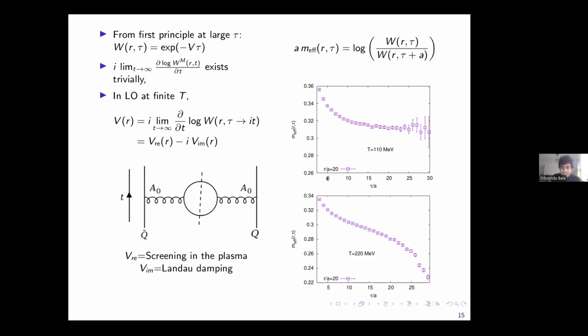But at finite temperature, as we just discussed, we do not see this plateau at all. What we have is a function that decreases gradually all the time, and we have to extract the potential from it. This tells us there is no pure exponential decay. How do I understand that? If we look into the leading order perturbative calculation of this potential, it turns out it's not purely real. It's complex, with a real part and an imaginary part at finite temperature. At zero temperature there is only a real part. At finite temperature there is an imaginary part, and this imaginary part makes the business complicated and is responsible for the fact that there is no plateau at all.